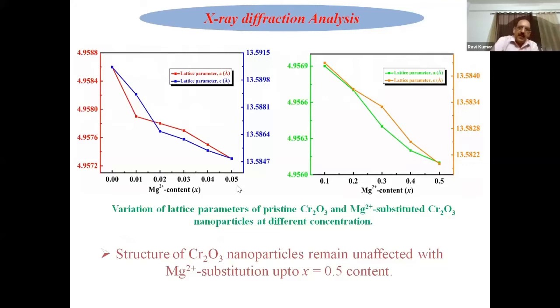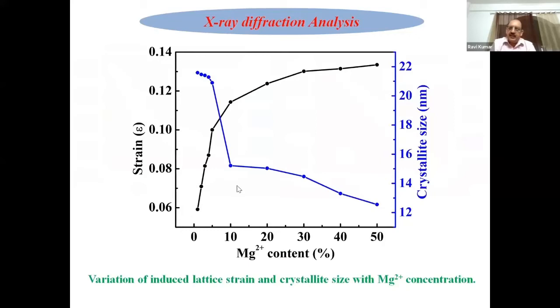First, the lattice parameter, as we are doping the magnesium, the lattice parameters are decreasing. Both a and c are decreasing. And at a low concentration, like up to 0.05x, or at a high concentration range, they are going in a similar fashion. Then if you see, the crystal size is decreasing with the substitution and the strain is increasing, because as the particle size is decreasing, the surface stress or surface strains are increasing. This is experimental data extracted from the X-ray diffraction technique.